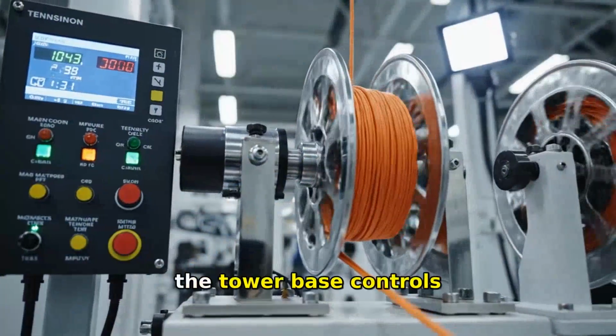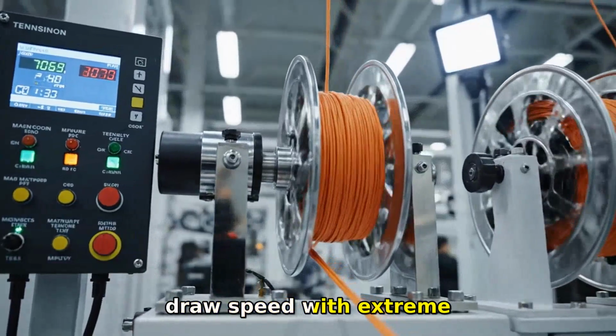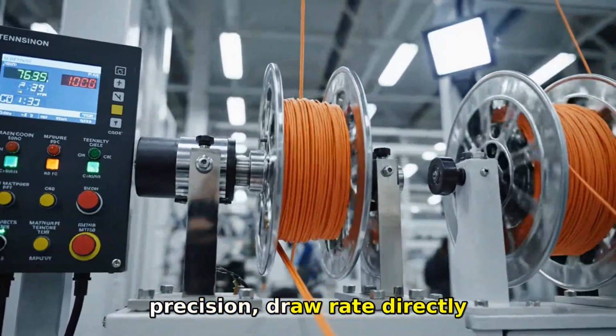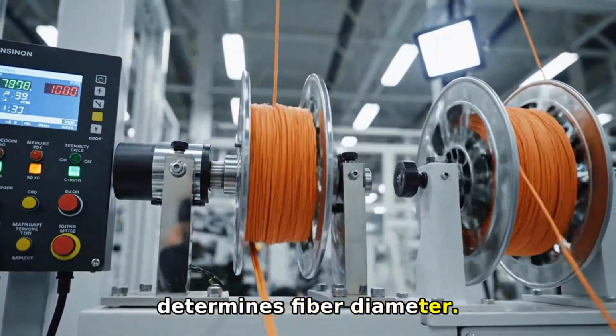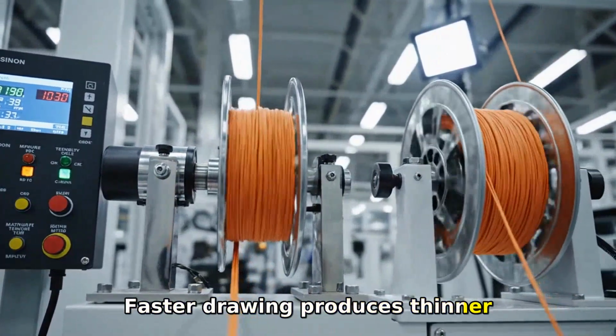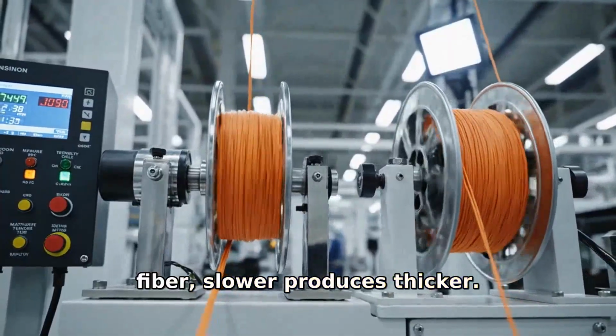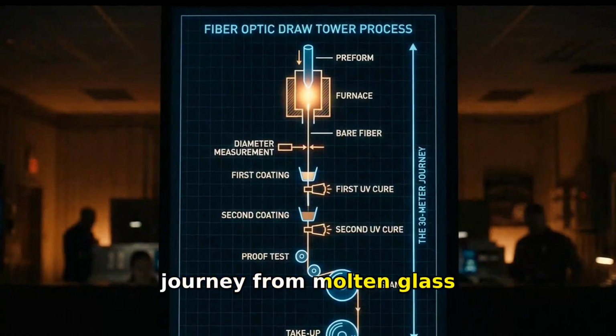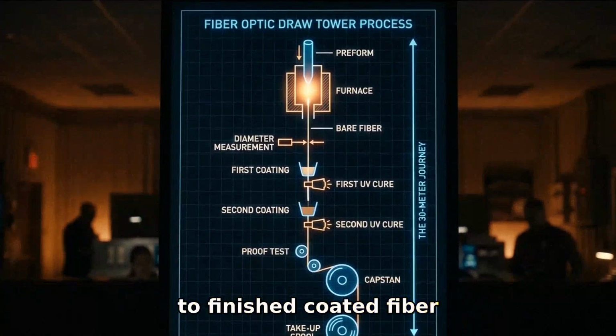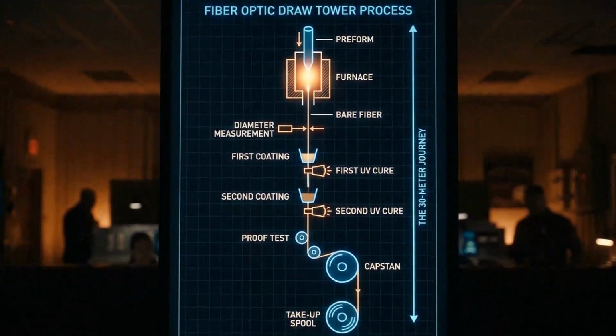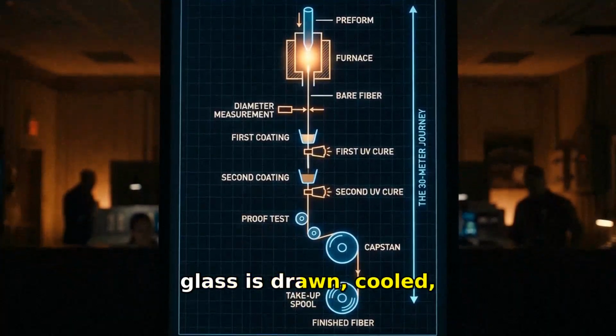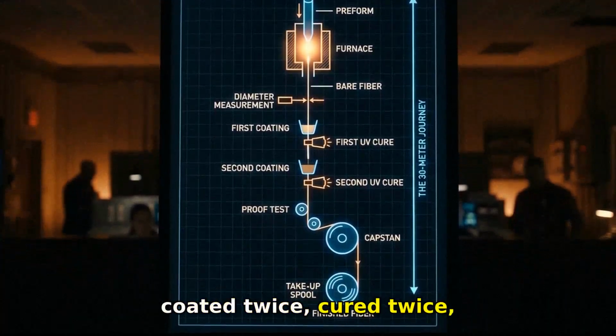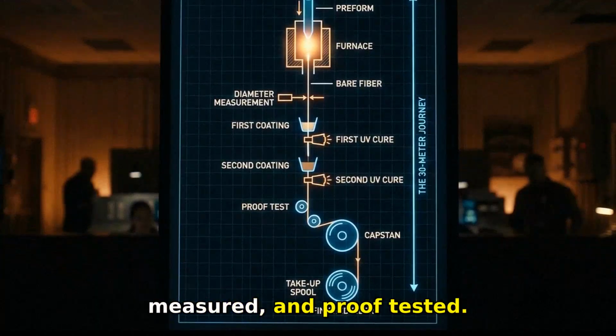The capstan wheel at the tower base controls draw speed with extreme precision. Draw rate directly determines fiber diameter. Faster drawing produces thinner fiber, slower produces thicker. The complete draw tower journey from molten glass to finished coated fiber takes less than 2 seconds. In that time, the glass is drawn, cooled, coated twice, cured twice, measured, and proof tested.